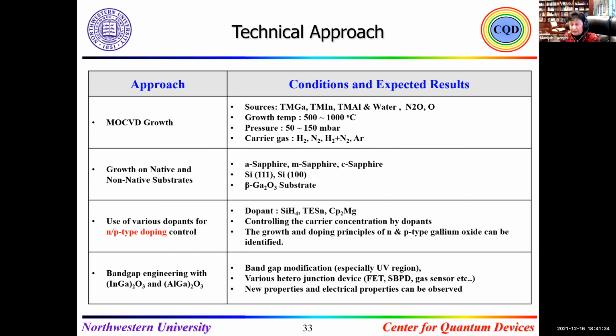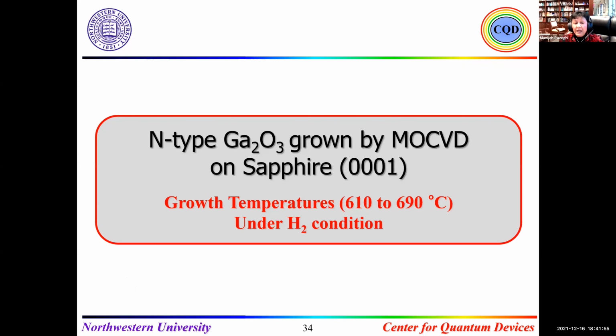But I knew we were working on that. So immediately in the reactor I showed you, where we were doing gallium aluminum nitride, I introduced deionized water, using it with trimethyl gallium. First we tried hydrogen as a carrier gas and sapphire as a substrate, doing trimethyl gallium with deionized water.